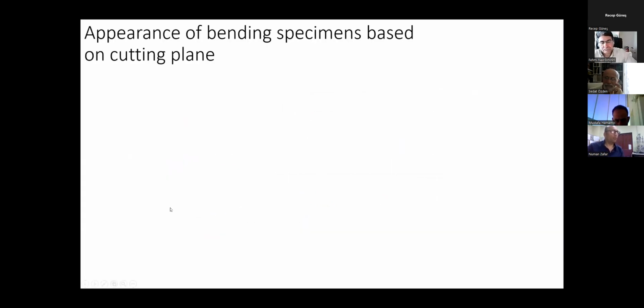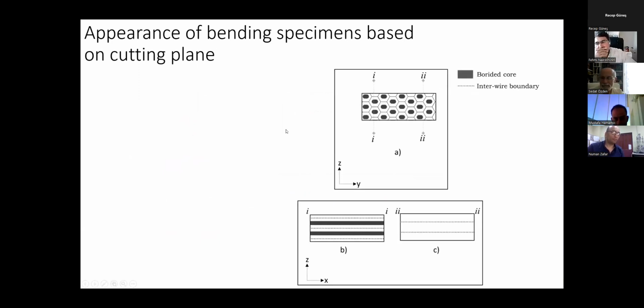Last few slides of this presentation. So we have cut the specimens, if you remember, in these planes, and depending upon the cutting plane, we can see the wire cores, dark colors represent the cores, and these are interwire bands. They were exposed, so we were able to see the type of cracks which were formed in which component of the wire reinforced bulks.